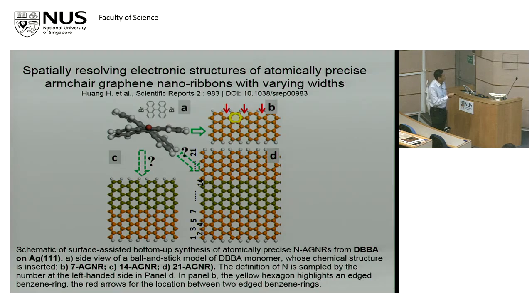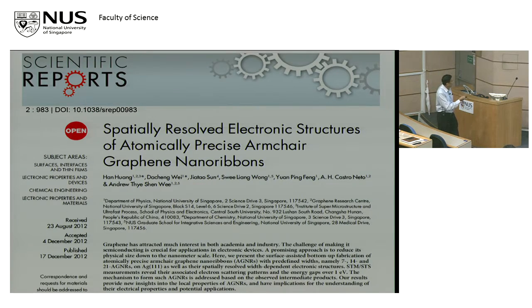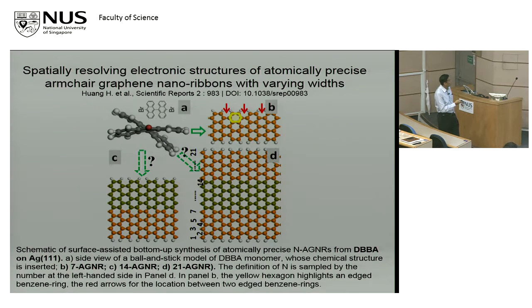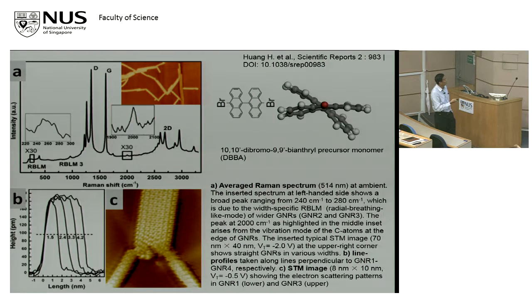So we did some work on silver, a different substrate. This is Huang Han again, to assemble this molecule. And this time, because the substrate was a little bit more reactive, we could make nanoribbons of different widths, because they did not just assemble in one direction, they could assemble sideways as well. So if you look at STM, you see different widths in multiples of 7 carbon atoms, because that's the width of the molecule that you started with. And of course, you can change it by using different molecules and so on.